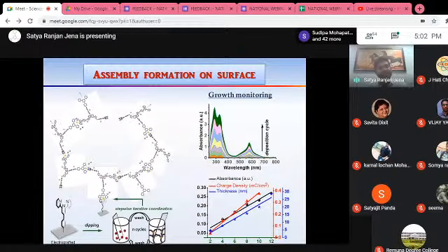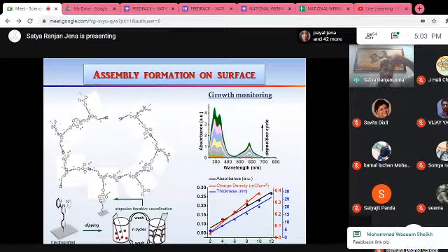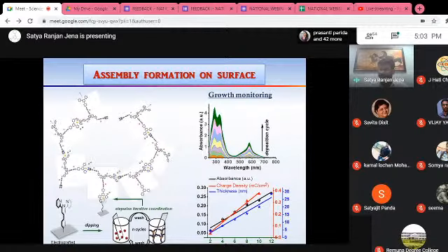Then we wash it, and again dip it in the ligand solution. Now only one terpyridine will bind, because it is a pseudo octahedral geometry. Iron is already coordinated to 3 nitrogens, so the other 3 nitrogens of the ligand terpyridine it will use to make the pseudo octahedral geometry, but the other two are still open outside.